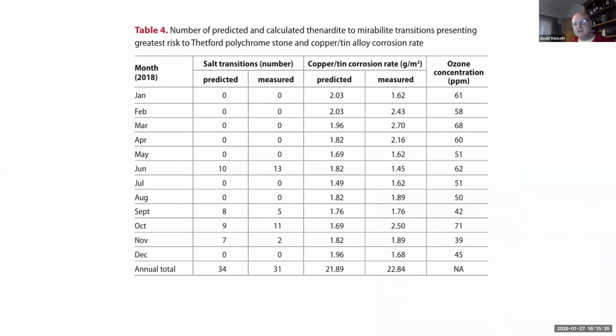And after we built it, we did some measurements of the copper corrosion rate, predicting it with the measured environmental parameters and measuring it with actually a piece of copper and seeing how quickly it corroded. Again, we had good correlations, so we think that's okay.